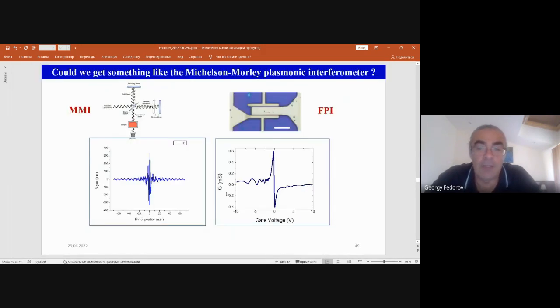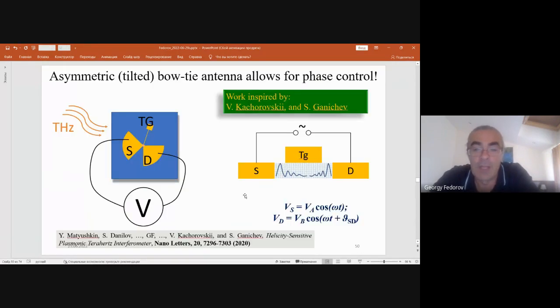Now, another story begins with this consideration that actually the Michelson-Morley interferometer is a bit better because you control the phase of the waves that reflect from the mirrors. And this is what we also did, but we did it in CVD graphene, so we don't see these nice resonances, but we see the effect of plasmonic interference. And I'm going to prove to you that this was really the case.